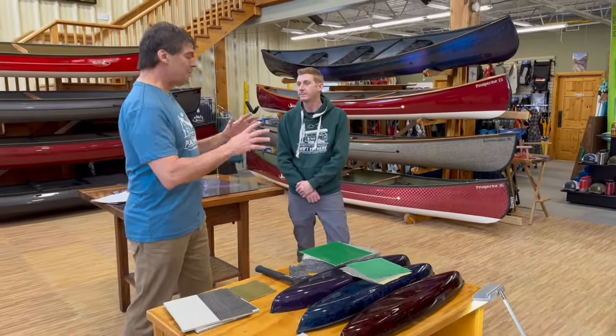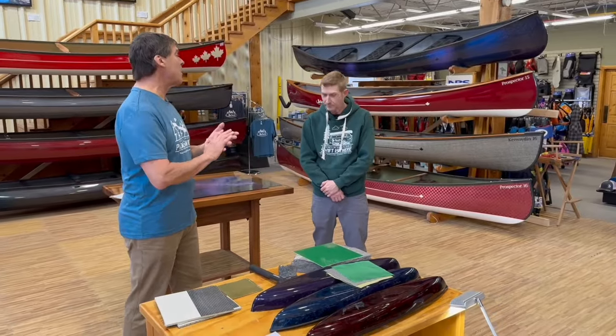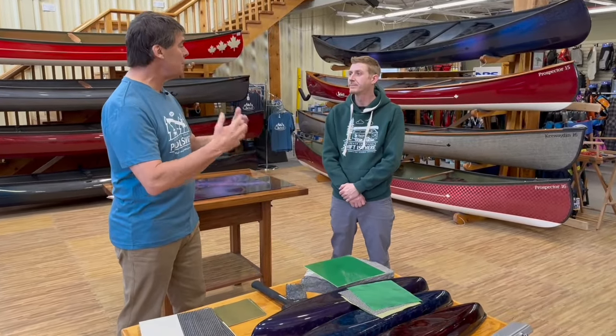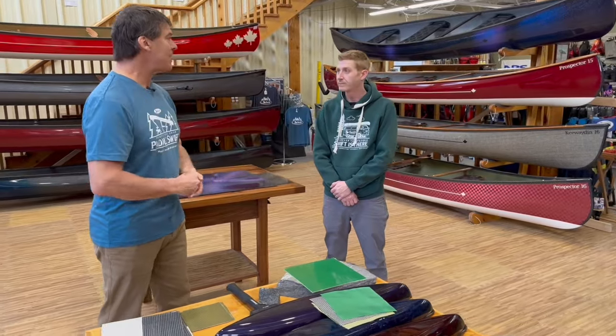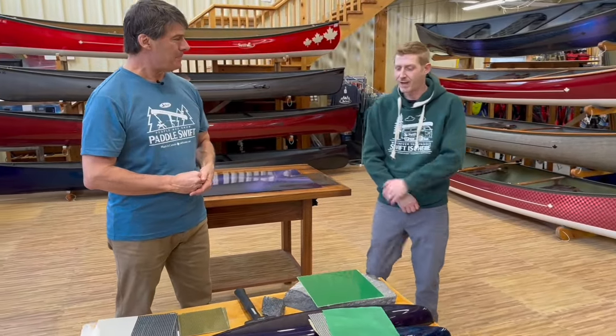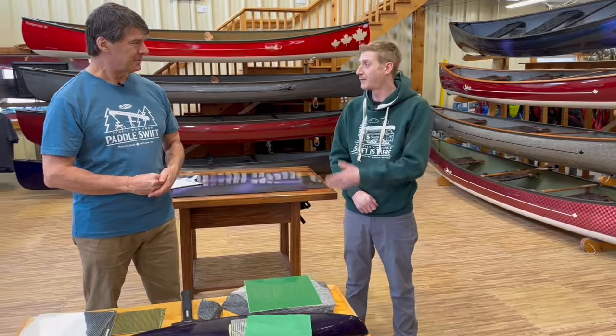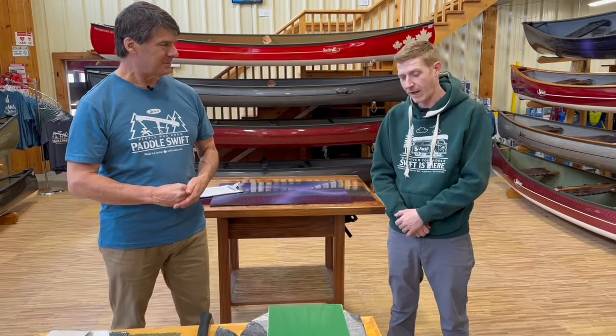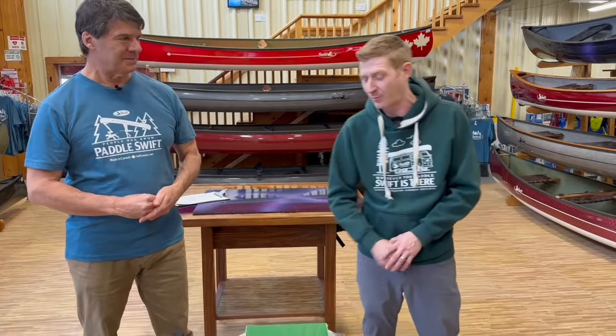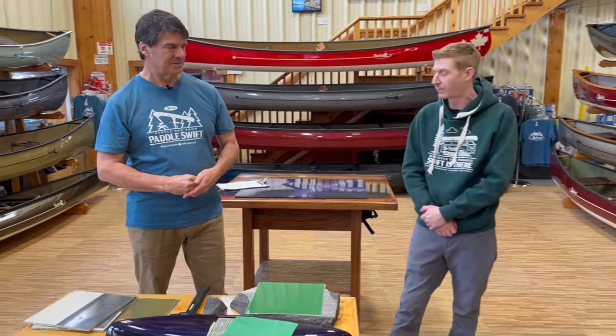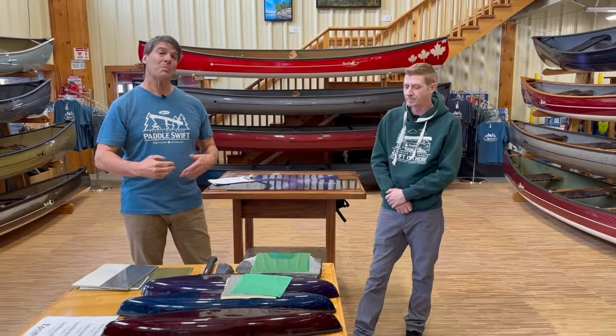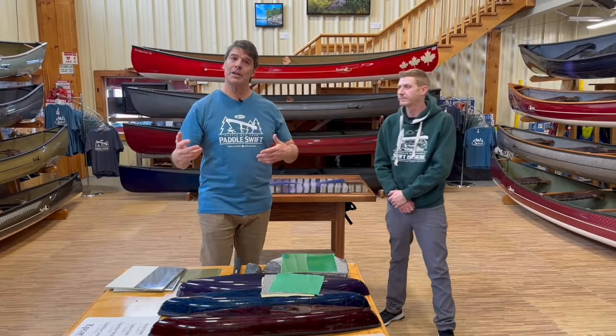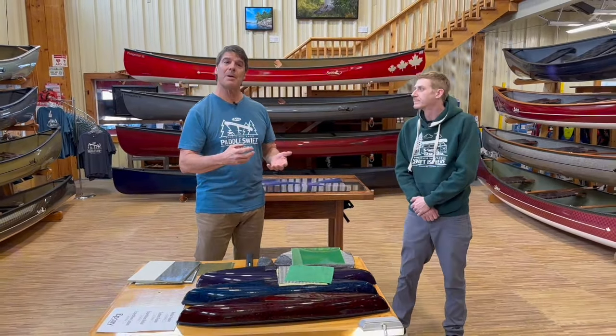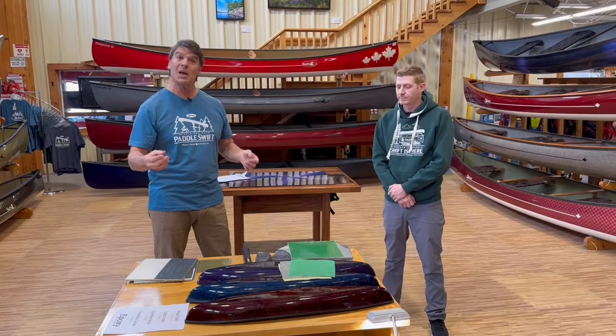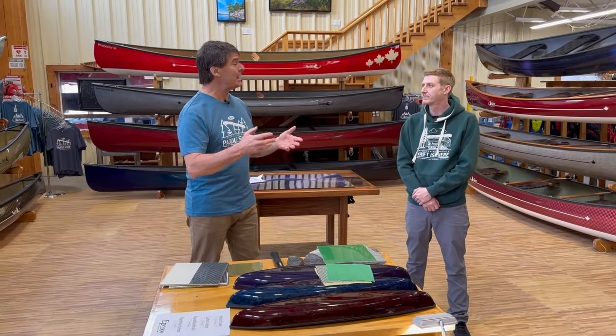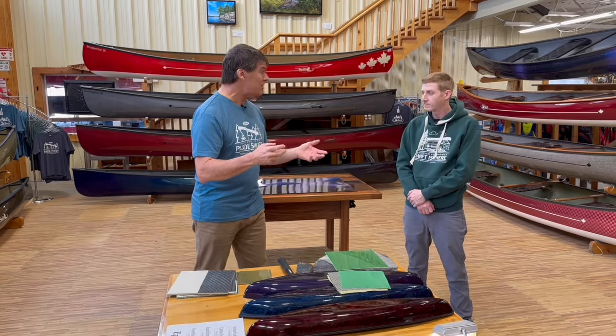Now, no material coating is gonna give 100% UV protection, but the UV Shield is a really enhanced form of it. Exactly. Even on cars and anything, the sun is a powerful thing. So anything we can do to deter it and help prevent it from degrading our laminates over time is a home run for us. Yeah. So Matt has been explaining to us over the years that the gel coat is typically about 15 to 20 mils thick. And now with the UV Shield, we're getting down to 5, 6, 7 mils in thickness.